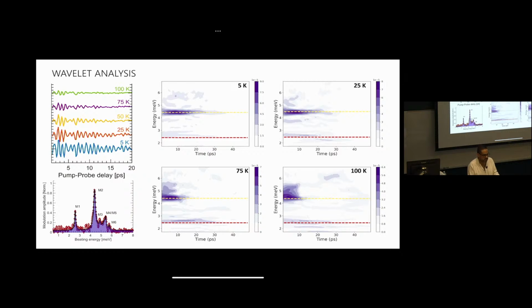Here, what we're doing is we're back to not just injecting photocarriers, and we're looking at the phonon coherence, the amplitude of this phonon coherence that we generate impulsively as a function of time at different temperatures. And this M2 phonon has a very strong temperature dependence because it's a highly anharmonic phonon. In order to get phonon-phonon interactions, you need anharmonicity. There's this other phonon here that is not very strongly temperature dependent, not very anharmonic. This guy is responsible for many of the population as well as the quantum dynamics that I've shown you. This is really a culprit of a lot of the optical processes that I've shown you. This one participates as well, but to a lesser extent.